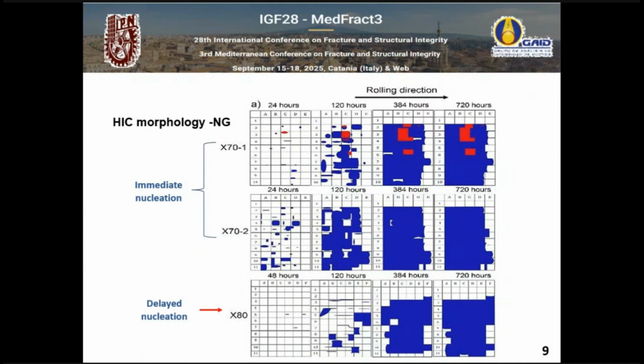We observe delayed nucleation, not as delayed as in the other steels, but still it took 48 hours to develop the first cracks in this X80 steel. The main difference is that the majority of the cracks have this elliptical shape. My students draw these crack locations as a square, but they are not square. They are elliptical.